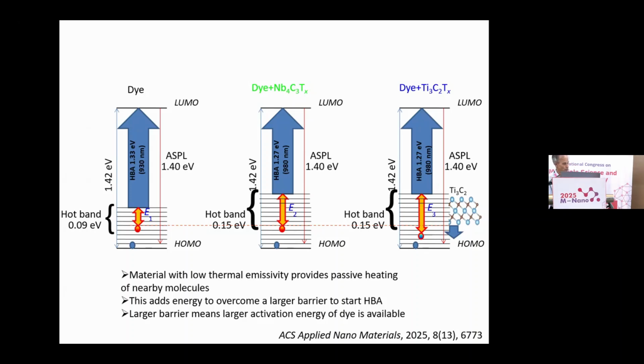Then we can extract electrons which are located deeper in the hot band. And this difference corresponds to the excitation energy. In order to excite the electron, we need to further lift this electron from the hot band, from some energy level which is occupied by this electron, to this energy level, in order to lift this electron to the singlet energy level. And this gap corresponds to the activation energy. This activation energy is dependent on the temperature and also on the passive heating or passive cooling effect of the system.